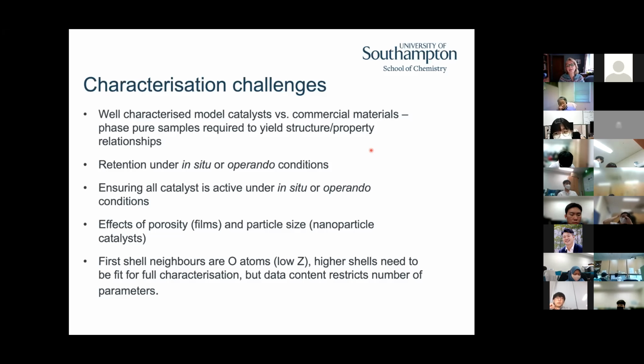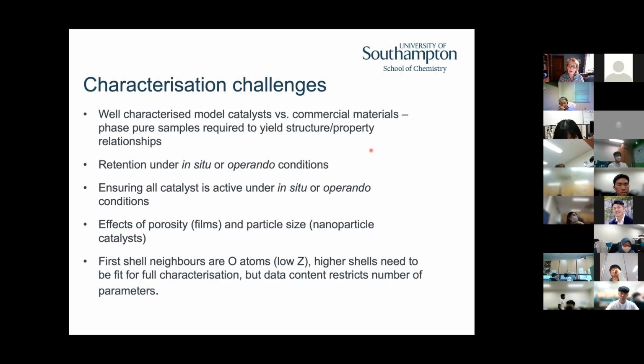If you want to get structure property relationships out of the data, you need phase pure samples to yield those relationships. You then want to know that that structure is retained when you start working under in situ or operando conditions. And actually you can learn a lot by just having these model systems and seeing whether that structure is retained. So for our gold particles, we saw that the shape of the particles changed. It's really important that every atom of the edge that you're looking at is active under the in situ or operando conditions. So we have to be very careful about loadings.